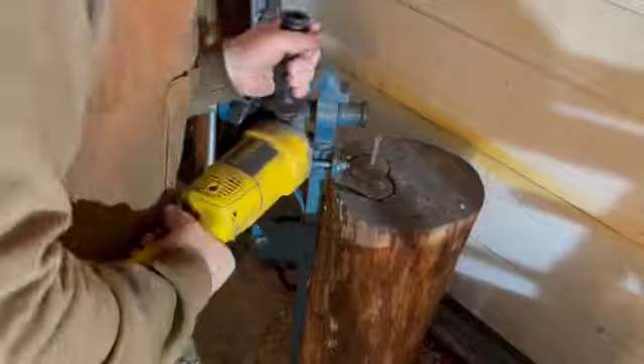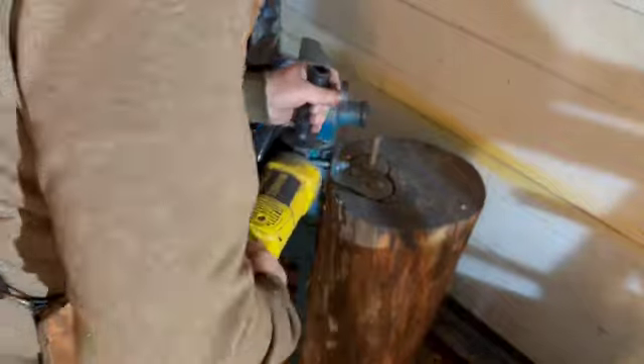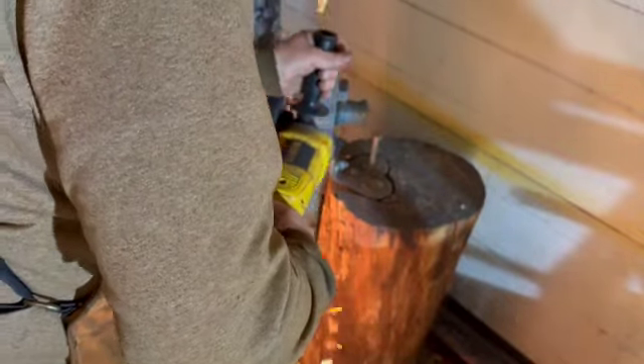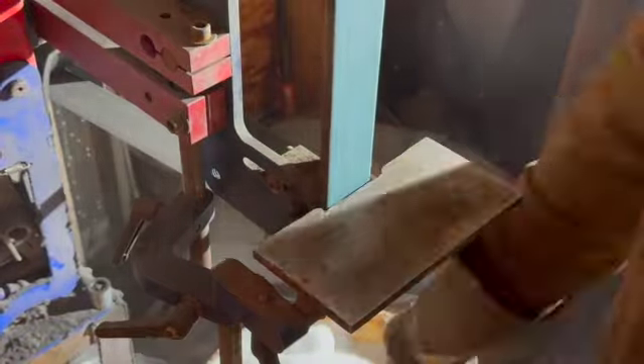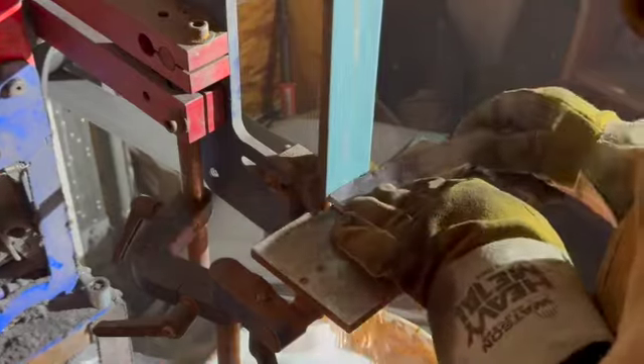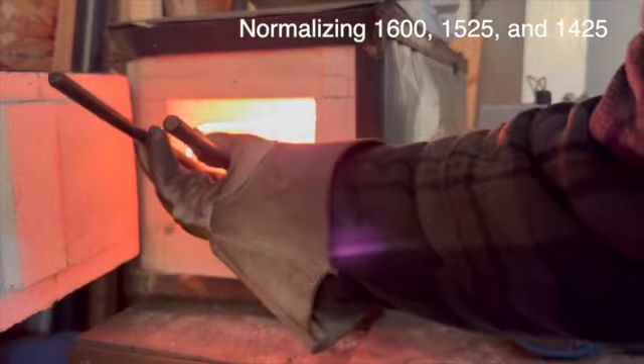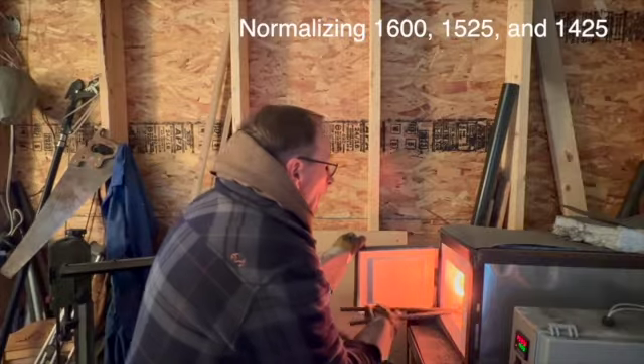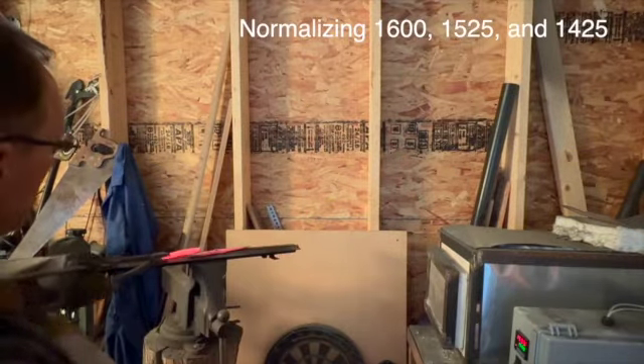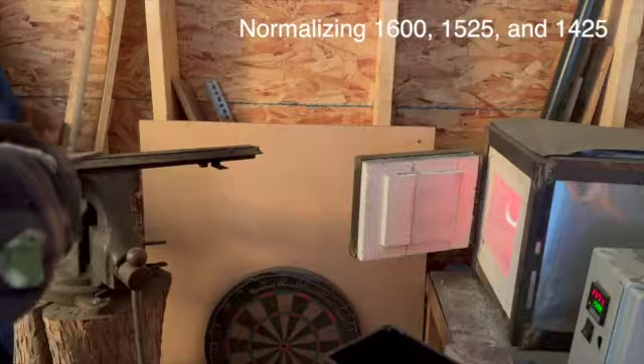Because I'm worried about heat treating this because it's such a small blade and the shock of quenching tearing apart that copper and steel, I'm going to leave it a little bit big, heat treat it, and then grind it to final shape. For heat treating, we'll start off with normalization. I'm going to do 3 normalization cycles at 1600, 1525, and 1425.